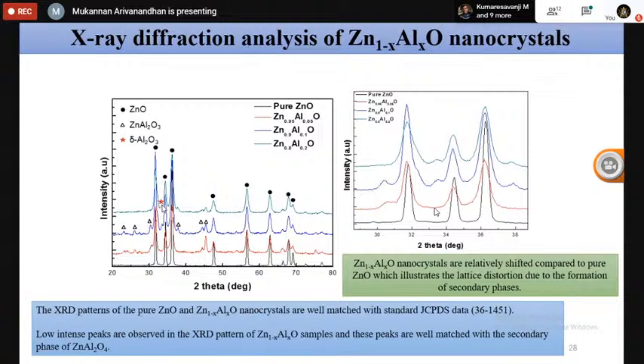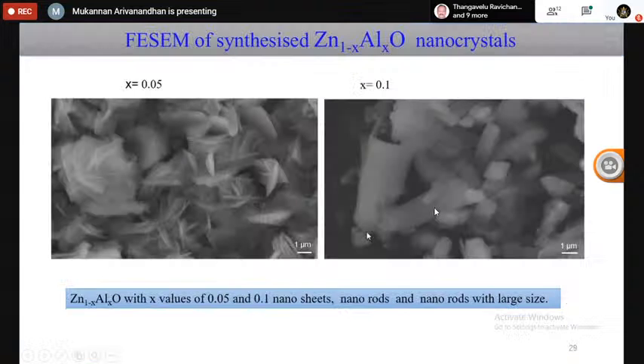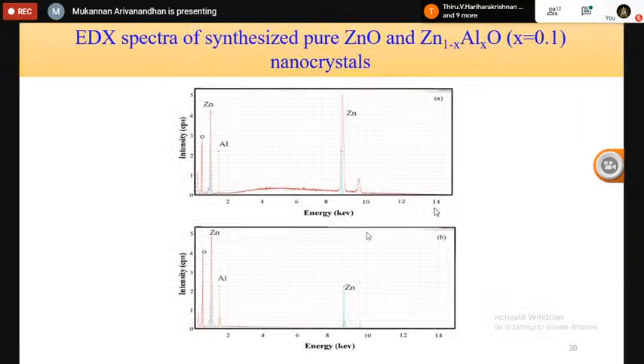Okay, so these three different phases have been obtained in the zinc aluminum oxide, and that is mainly due to the very low solid solubility limit of aluminum in zinc oxide. And the substitution of aluminum has been confirmed by a systematic shift in the diffraction peaks. The morphology also changed with respect to the aluminum content, from sheets to a rod-like morphology. And the presence of aluminum has been confirmed by the EDX analysis.